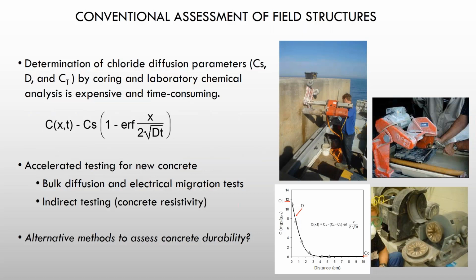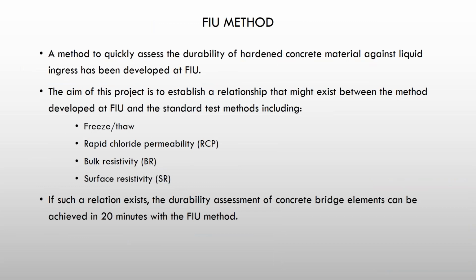The determination of chloride diffusion parameters is typically done by coring and laboratory chemical analysis. They are expensive and time-consuming. Alternate methods for new concretes involve bulk diffusion, electrical migration tests, as well as concrete resistivity tests. The alternate method we developed here at FIU quickly assesses the durability of hardened concrete material against liquid ingress.